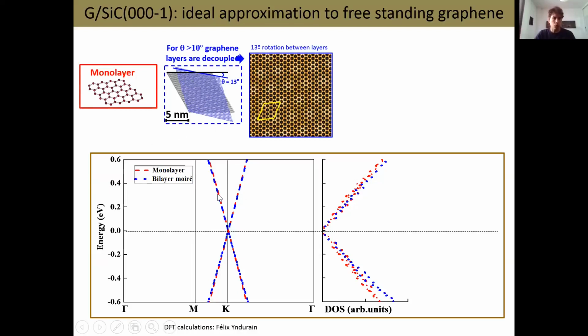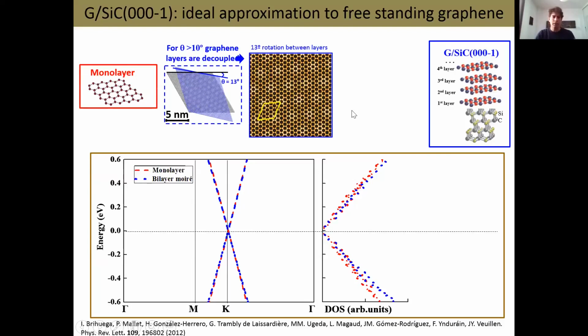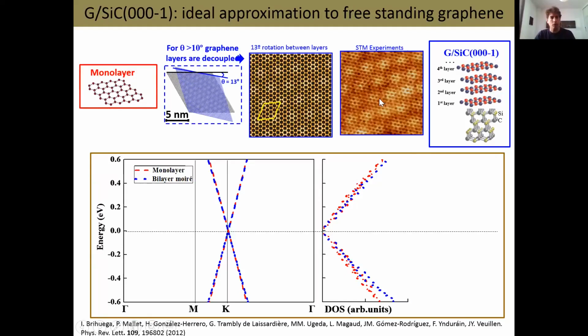So now here in blue, you have the calculations for the twisted bilayers, and that's for a 13 degrees rotation. And then you can see that the band structure at low energies is essentially identical to the one of pristine graphene. And the same happens for the density of states. So that's a very good approximation for freestanding graphene. And the good news is that this kind of sample, we can have in practice, because if you grow graphene on the silicon carbide face, then graphene grows with these different rotational angles, and then you can find on the surface regions which have this large rotation angle.